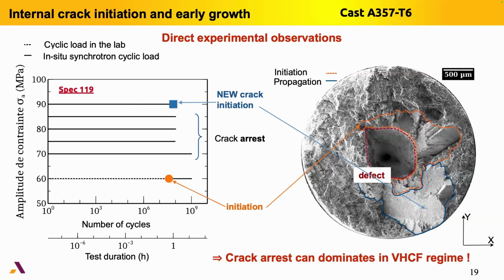So you can see here, for instance, after we have broken the specimen in a voluntary manner under quasi-static loading in order to observe the internal defects. And you can see here the defects. The original crack is here, and the second crack in blue is here, and the second crack has initiated here on the left and then propagated.